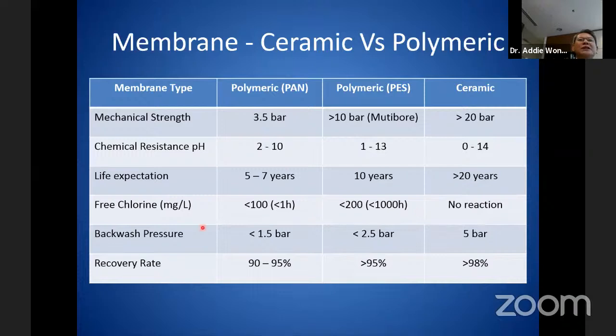For backwash pressure, polymeric membranes can't take such high pressure. Normally in practice ceramic uses a 5 bar high pressure backwash. Instead of using filtered water to backwash, the system can use air to push out what is remaining in it. So you can have very high recovery, 98%, compared to 90 to 95%, which is already quite high.